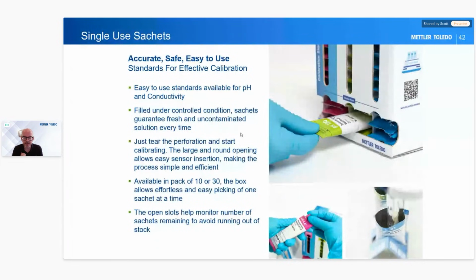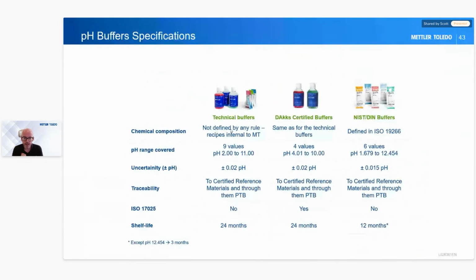This is more about single-use sachets. It shows you here, we have dispensers showing them off. They're available in packs of 10 or 30, depending on what you need to do. What this really does is improve your accuracy when you're taking calibrations, because it's sealed inside there and it's single use, and when it's done, it's thrown away as well. So this is a list of everything we've got. So different values, and then the uncertainty here you can see is plus or minus 0.02 we talked about before. Different ones have different shelf lives depending on what they are.